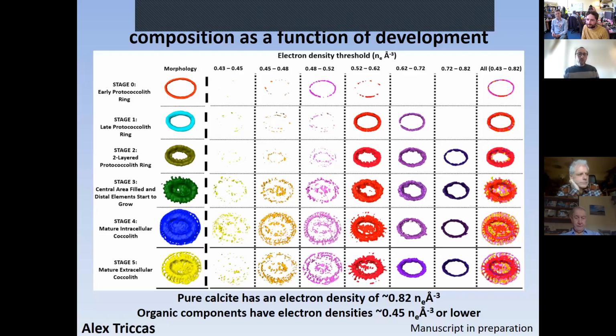From what people talk about in the literature, you have polysaccharides coming in mostly once the ring of calcite has nucleated. So that would have been once we have this kind of structure in here, and then the crystals start growing in different directions. That's when more polysaccharides start coming in. So it could explain why we started seeing this lower electron density. But again, if you go back to how much polysaccharide is actually in there, that's what I find challenging, because you need quite a lot of polysaccharide to cause this decrease in electron density, basically.